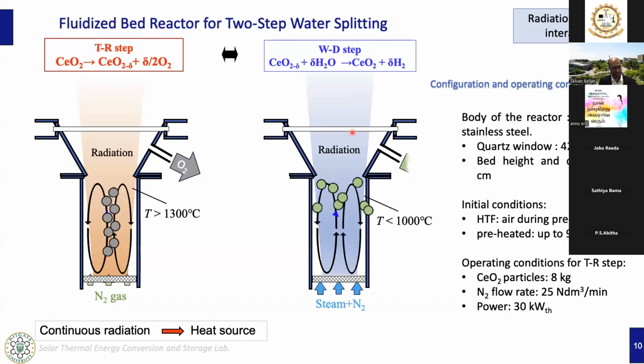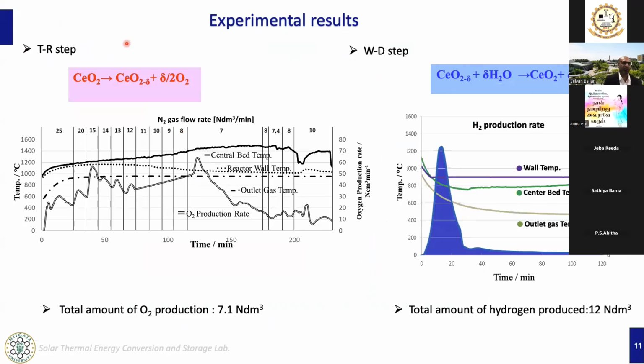And here you can see our experimental results. Here you can see the central bed temperature as a function of time, the reactor wall temperature, the gas temperature, and the oxygen production rate as a function of time. As you can see, at the end of the first step, we produced around 7 liters of oxygen.